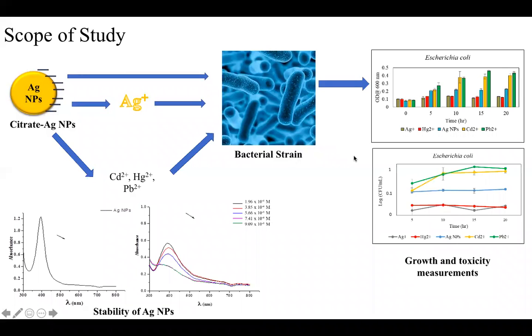For us, we also wanted to take a look at how cadmium 2+, mercury 2+, and lead 2+ impact the stability of silver nanoparticles over time. So we observed how that change in stability occurred and what influence that had on bacterial strain growth. We were able to do that by looking at optical density studies over a 20-hour time frame in 5-hour increments.